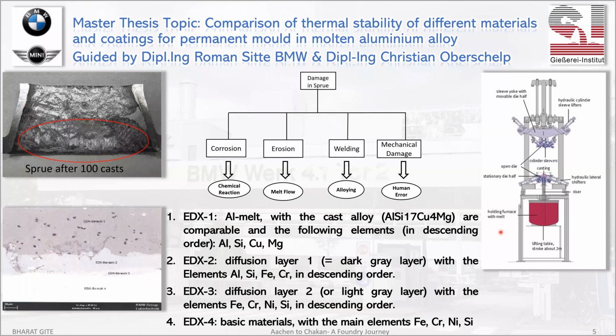Further, a desire to work in an industrial setup brought me to interviews at Mercedes-Benz, Stuttgart, BMW, Landshut, and Georg Fischer in Schaffhausen in Switzerland, alongside exploring Europe for myself. Mr. Roman Sitte, my guide at BMW Foundry, stated the problem in low pressure die casting of cylinder blocks and heads, having trouble of frequent change of the sprue, keeping the machine idle for a few minutes, resulting in lower productivity. We can see here the sprue after 100 or 80 casts, it was getting eroded, and they used to weld it or replace it. That replacing time was keeping the machine idle.